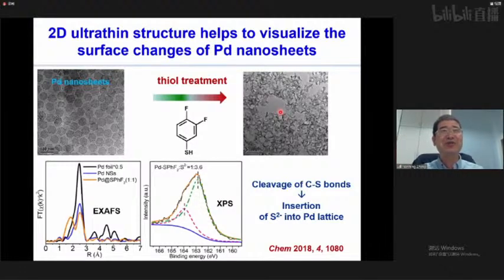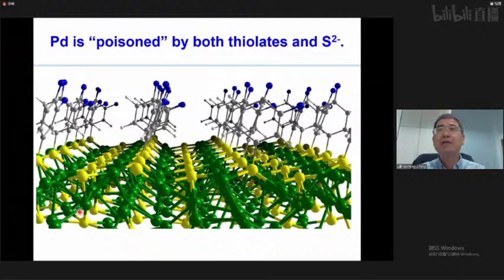Because the thickness is so small, we are able to use X-ray absorption spectroscopy to resolve the structures. After careful studies, we found that the palladium can cleave part of the sulfur-carbon bond. So some of the sulfur penetrates into the palladium lattice. That's why the palladium sheets get highly distorted. But on the surface, we still have the thiolate modification. From this structure, I think you might already have some chemical picture in your mind, right? The thiolates must create some steric effect, and the penetration of sulfur into the palladium lattice should create some electronic effect, because the palladium lattice has been changed.